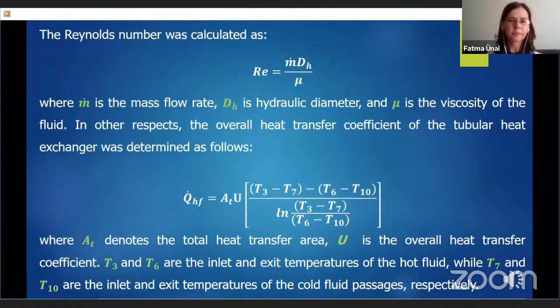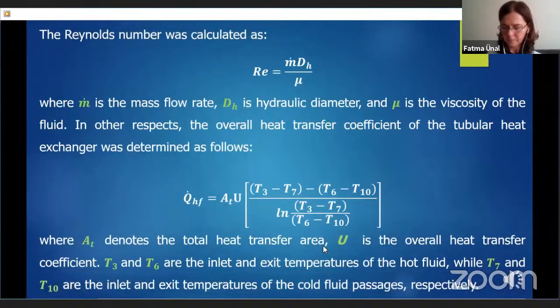The Reynolds number was also calculated using this equation. In this equation, m dot is the mass flow rate, dH is the hydraulic diameter, and mu is the viscosity of the fluid. In other respects, the overall heat transfer coefficient of the tubular heat exchanger was specified using this equation, where AT denotes the total heat transfer area, U is the overall heat transfer coefficient, T3 is the inlet temperature of the hot fluid, T6 is the exit temperature of the hot fluid, while T7 and T10 are the inlet and exit temperatures of the cold fluid passage respectively.